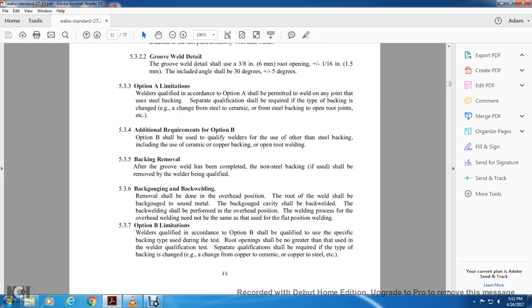Option A limitation. A welder qualified in accordance with Option A shall be permitted to weld any of the joints using steel backing. Separate qualification shall be required if the type of backing is changed, e.g. a change from steel to ceramic backing, or to open root joints, etc. 5.3.4 Additional requirements for Option B. Option B shall be used for qualifying welders for the use of backing other than steel, including ceramic, copper backing, and open root welding. 5.3.5 Backing removal. After the groove weld has been completed, non-steel backing, if used, shall be removed by the welder being qualified.